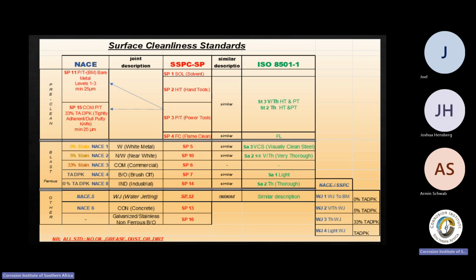Right. So it's a subjective measure when you say moderate. It's a visual. These are all what they call visual standards. And what's nice about these, what we have done recently, you'll see I've added into this chart here the actual percentage that you allow. They have a surface area that you measure, typically 10 square meters. And in that 10 square meters, you evaluate a 3 inch by 3 inch, 75 mm by 75 mm area. And that area is allowed to have either nothing, or 5%, or 33% of flashback on the surface.